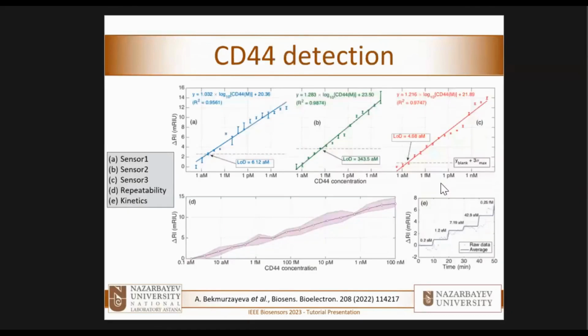And here is how the detection performs. So we have done here multiple sensors. We have 3, but in reality we have much more than 3 to show that we have a dependence on the concentration of the analyte that is quite log linear. So for an exponential change of the concentration, we have an incremental change of the output, which here in this case is normalized by the sensitivity of the sensor. So the sensor is extremely precise because, as you can see, even concentrations of a few attomolars already give a response.